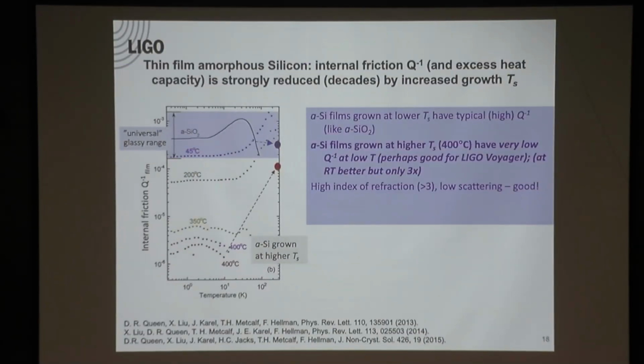And this is the work that got me the attention. What this shows is if I grow amorphous silicon at room temperature, which is where most people grow it, I have an internal friction, mechanical loss, that is up here in this so-called universal range. There's the silica curve, that's a very typical glass. There's the silicon curve, nothing remarkable about it. It's a little lower, but it's nothing remarkable.